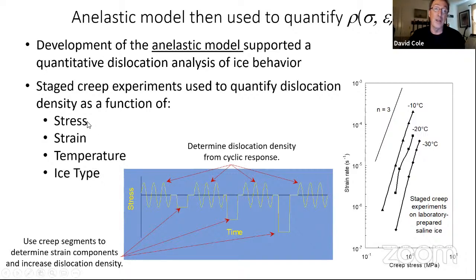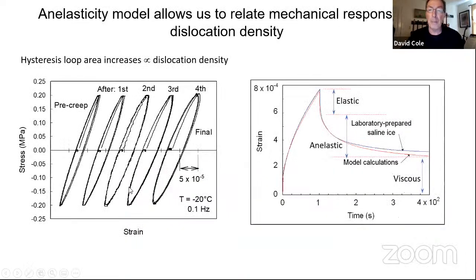And after about a year's worth of experiments as a function of stress, strain, and temperature at ice type, we were able to develop the relationships we'll be looking at in a second, which lets us track the dislocation density as a function of those variables. This just shows you what the hysteresis loops look like. And you can see the loop area is increasing with strain history here, and that's what lets us track the